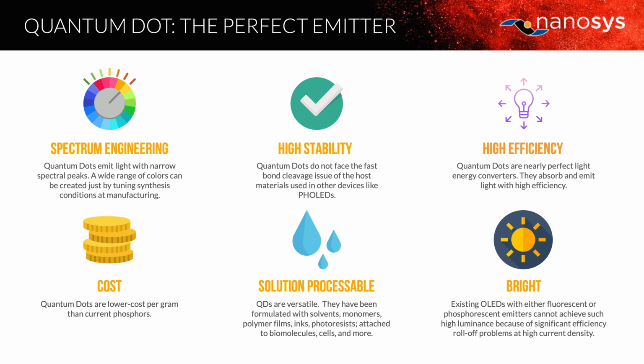Last but not least, quantum dots can be used in multiple modes. So we have the photoluminescent mode, which everyone's familiar with, where we're exciting with a high energy photon and down converting. But there's also the electroluminescent mode, such as when we are driving electrons and holes into the quantum dot, as we see in this EL display that I have here. Flexible, printed, no vacuum deposition technology here, and welcome to San Diego. Very nice and bright, very high efficiency at around 17% EQE.